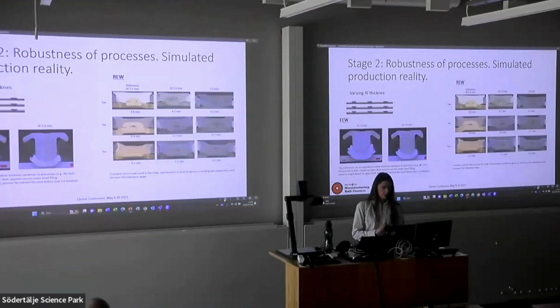And then maybe the most important thing, varying aluminium thickness, which is of course very important when we have these cast components, because they tend to vary a lot in thickness. And here we tested joining with the same parameters from the reference being 3 millimeter aluminium. And here we instead tried to join 2.6 millimeter and 3.4 millimeter. So for friction element welding, you can see that when you decrease the thickness, you get more of an underhead filling, which is not desired.